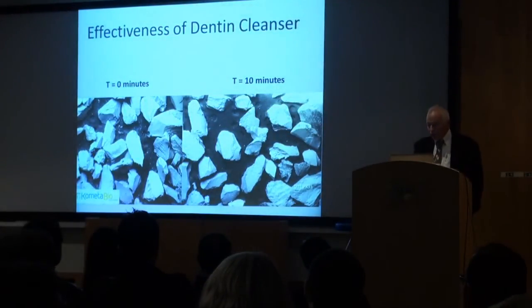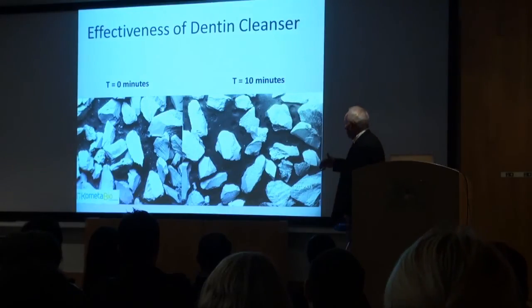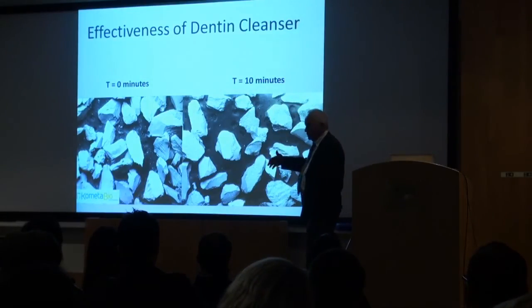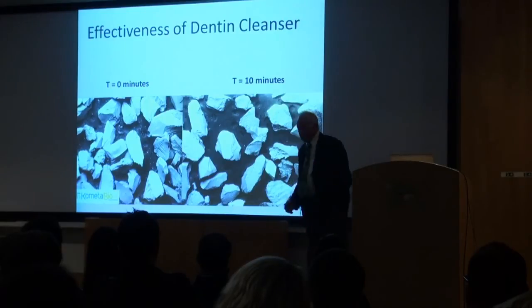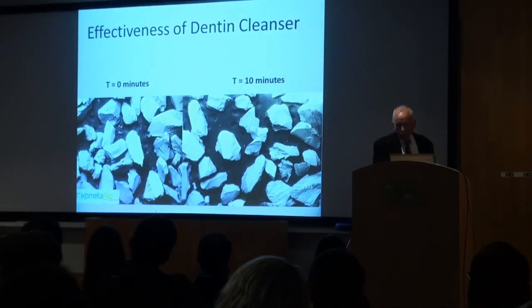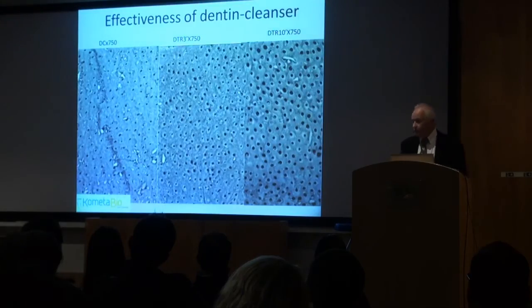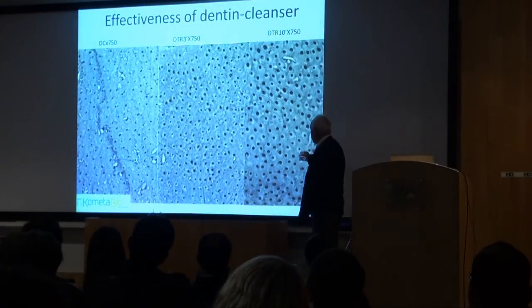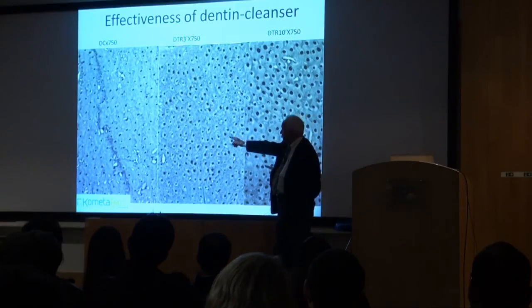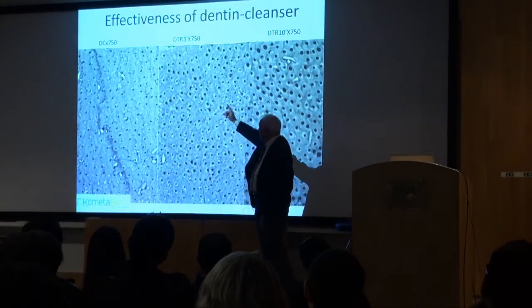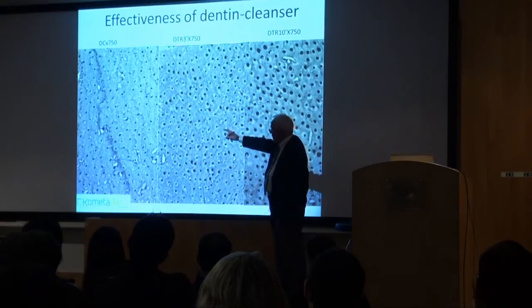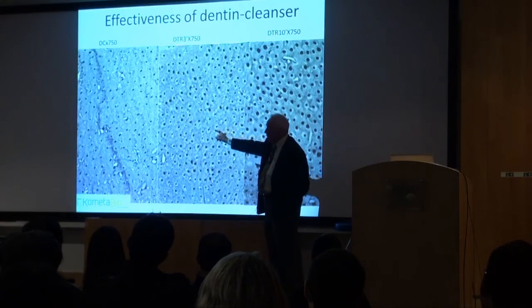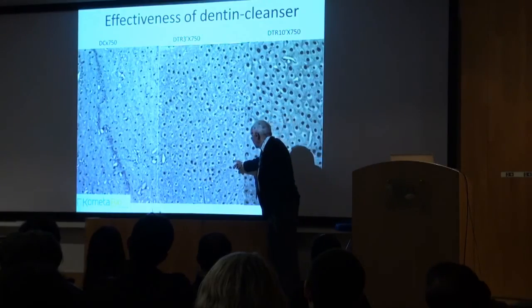We tried to understand how much time we need to have a bacteria-free product. We found that after 10 minutes we have a beautiful result. You can see, starting here from time 0, all at the same magnification, the dentin tubuli openings are very narrow. Here, after 3 minutes, they are much wider.